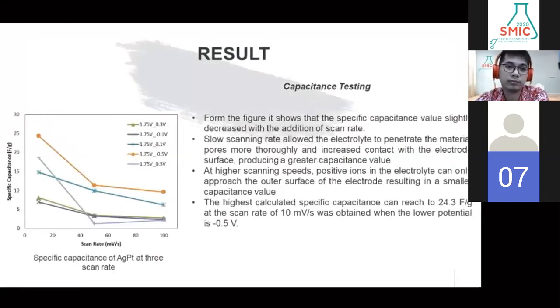Next is capacitance testing. From the figure on the left side, it shows that the specific capacitance value slightly decreased with the increase of scan rate. And here we use 3 different scan rates. A slow scanning rate allowed the electrolyte to penetrate the material pores more thoroughly and increase contact with the electrode surface, producing a greater capacitance value. At higher scanning speeds, positive ions in the electrolyte can only approach the outer surface of the electrode, resulting in a smaller capacitance value. And here, the highest calculated specific capacitance, 24.3 farad per gram at the scan rate of 10 millivolt per second, was obtained when the lower deposition potential is minus 0.5 volt.